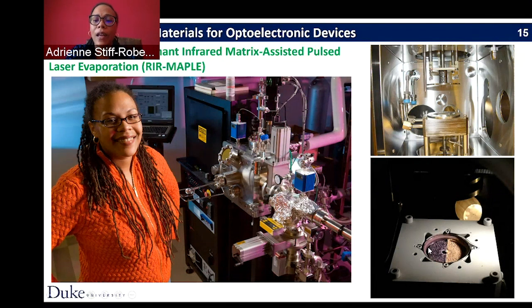So another development that we've done that actually I've patented is what we call the donut configuration. So there we have an inner circle and an outer annulus, and they have the two different materials there. And the reason that's important is by controlling the raster pattern and the dwell time, you can control the composition. So we've actually demonstrated things like a gradient composition because we can control the dwell time inside and outside the cup, so we have complete flexibility in what the composition is of the film.